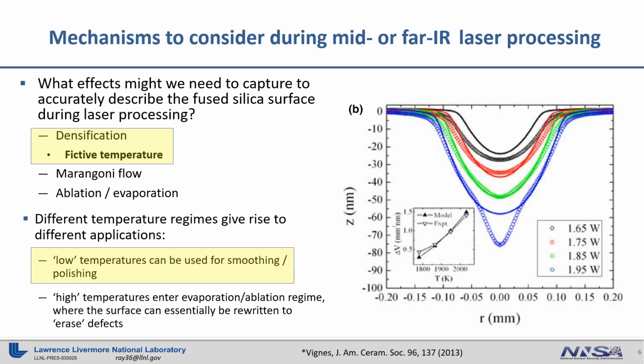And so you can imagine there was a CO2 laser just parked on top of the fused silica. And what we're looking at are the surface profiles following irradiation. So you see different powers cause different levels of deformation in the fused silica surface. So if you can take advantage of that, then you can basically polish an optic with a laser. And so that's what I'm going to be discussing.